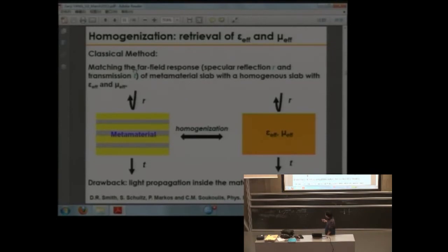So there is a classical method which can treat the homogenization for optical metamaterials, which is to extract the effective parameters, the effective permittivity and the effective permeability, from the reflection and the transmission coefficients of a metamaterial slab. There are a few problems with this classical method. A major one is that in this retrieval process, only the far field quantities are involved,